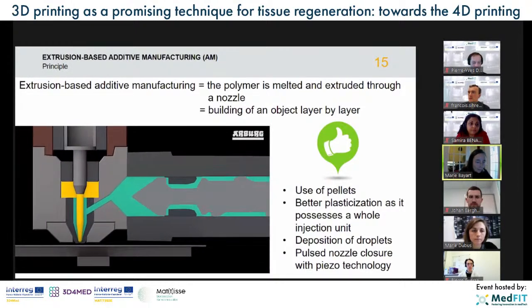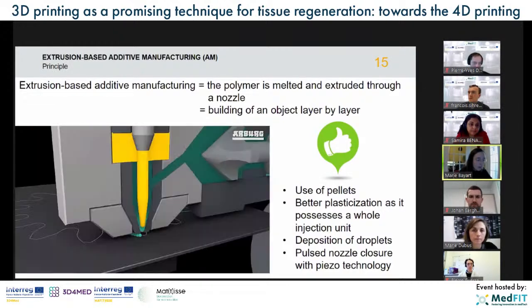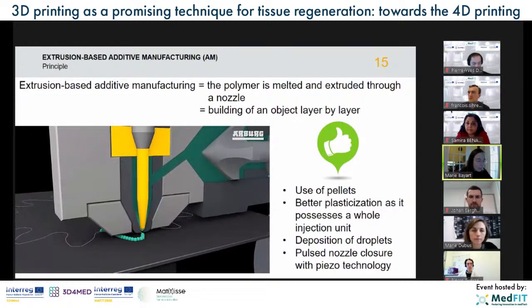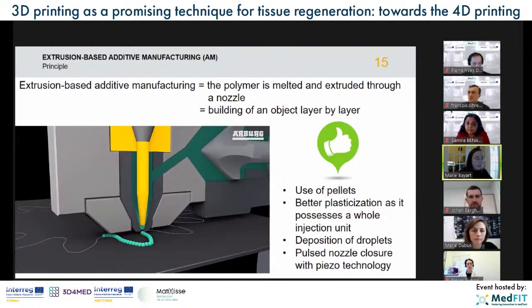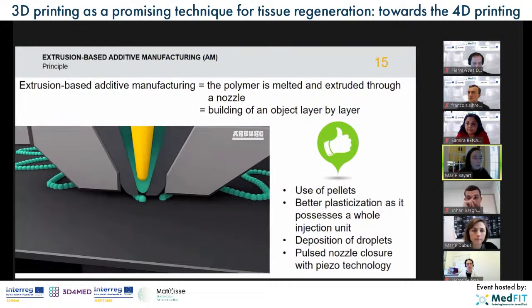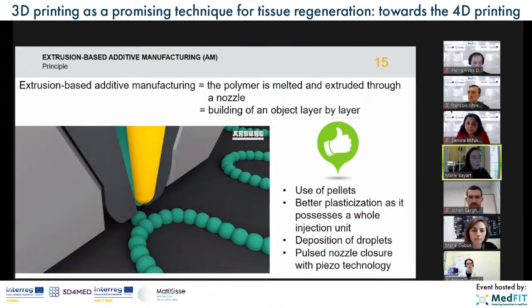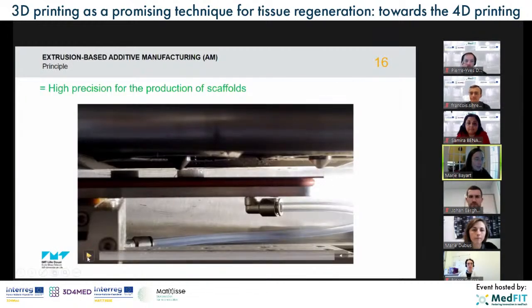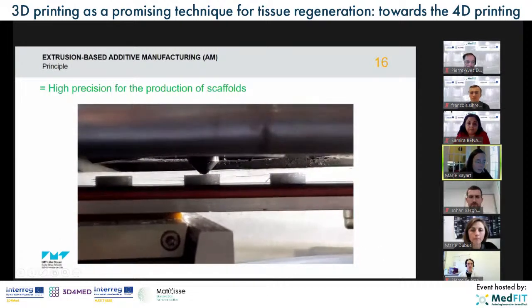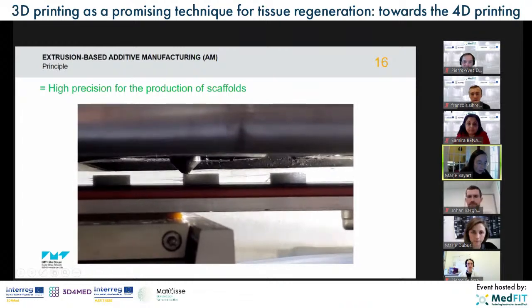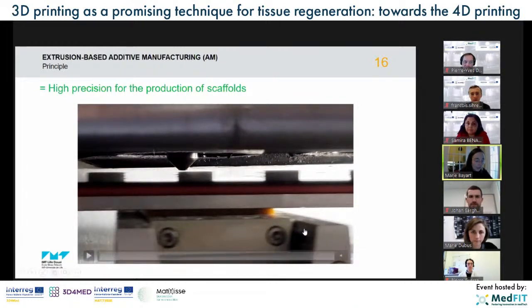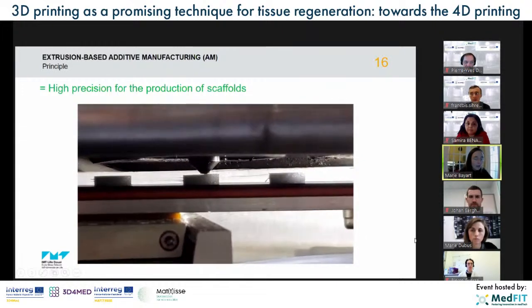And just after that, a pulsed nozzle closure enables the deposition of droplets and not filaments as in the other techniques. So the droplets are deposited here on the first layer. And when this layer is over, the building platform will move down and the second layer will start to be deposited, and then until the last layer, the platform will move down and finish the work. So in the next slide, you can see that it has a high precision for the production of scaffold. Here you can see the droplets being deposited on our scaffold, and it also enables to print several scaffolds at the same time. So here we print 5 scaffolds at the same time.